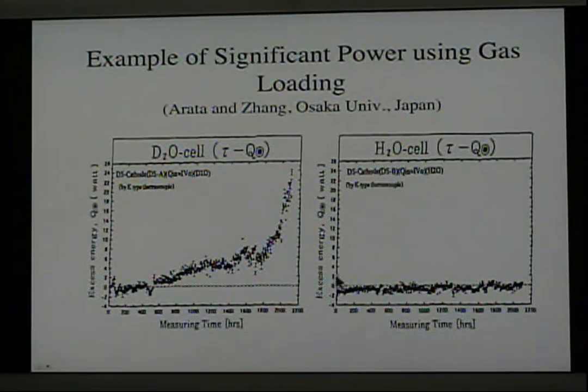If the sample is electrolyzed in light water, this effect does not happen. So you can see that simply exposing an active material to pressurized deuterium is sufficient to generate excess power. And I might add, helium and some tritium has also been found to be produced by this reaction.